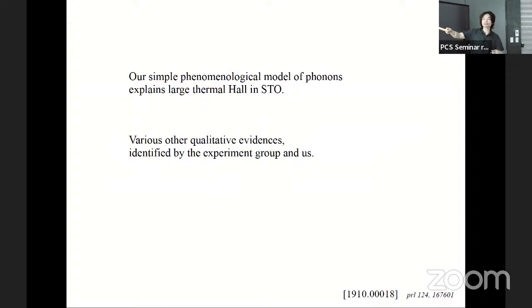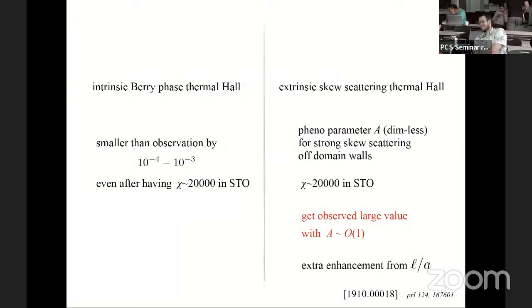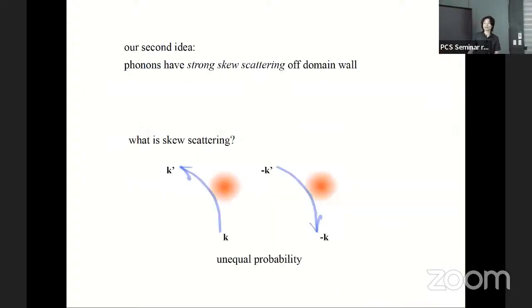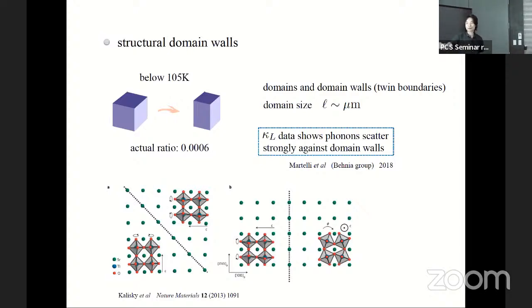And moreover, this explanation is compatible with other qualitative evidence in the experiment, whose details I'm not going into. Do you have some intuitive explanation why this skew scattering is really large? Right. We think it's because the Berry curvature is large and also the scattering is strong. So we combine the effect of both, and it's just as simple as that. We don't have a detailed mechanism for how the scattering occurs. We can study more models. Right, because the twin boundary is very complicated. In this twin boundary, it's proposed that there are some weird degrees of freedom living on the twin boundary that has not been very well studied.